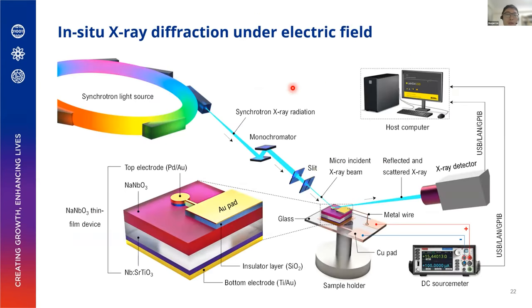Okay, so this actually is related to one last slide about the X-ray part. What we want to design is to bring this device into a synchrotron to do in situ X-ray diffraction under electric field to understand how the lattice changes. Actually the strain response is very huge. So we want to understand whether this is coming from pure lattice change, or whether there is an extrinsic contribution like domain wall rotation, these kinds of things.